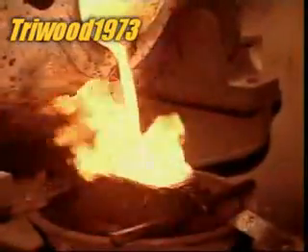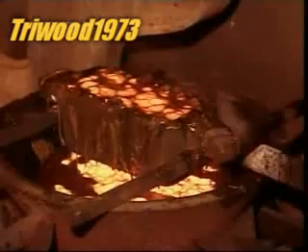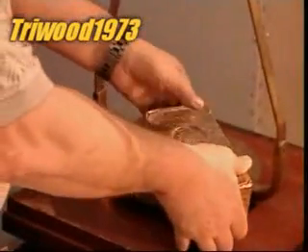If it does contain gold, it goes back in until it's gold free. By now the gold has cooled slightly, so they reheat it to 1,600 degrees Celsius, then cast it into bar-shaped moulds. The gold takes about 4 minutes to solidify, then another hour to cool completely in a basin of cold water. The gold bars are extracted from the moulds and cleaned of any slag residue.